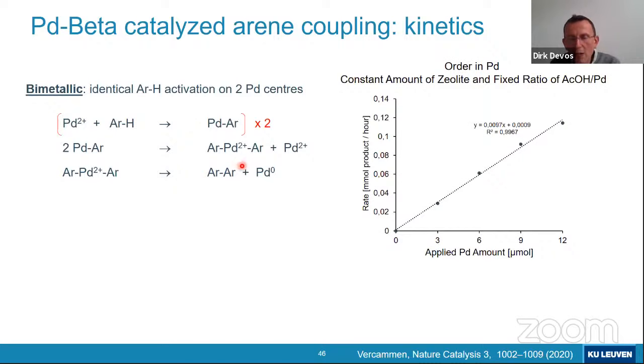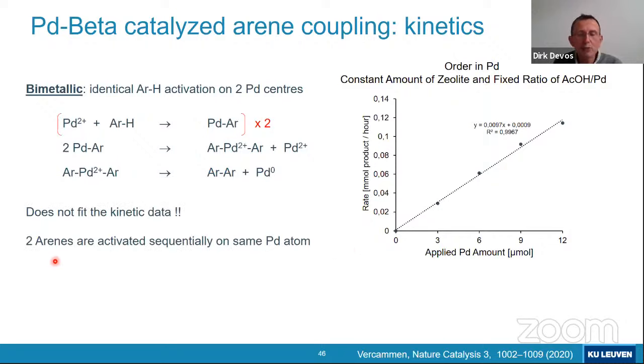And then, of course, you can start to wonder, can we deduce also something from these kinetics regarding the mechanism? It's always very tempting to say that such an arene coupling would be a bimetallic mechanism, which is shown here in very simplified form, meaning that each of the arene partners would be activated on a separate palladium. Then you would expect that you need a transmetallation, transferring 1 aryl group from 1 palladium to another to make this bis-aryl palladium intermediate, which would then do a reductive elimination and produce the bis-arene. And then you could expect a second order in palladium, but that's not what we saw. We saw actually a definite first order in palladium, which hints that it's likely that the 2 arenes are activated sequentially on the same palladium atom.